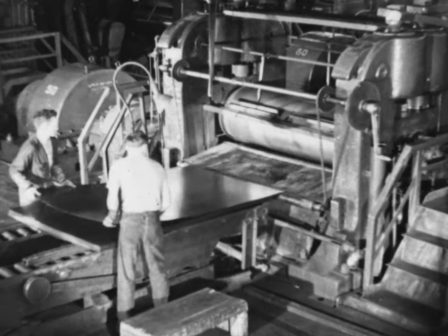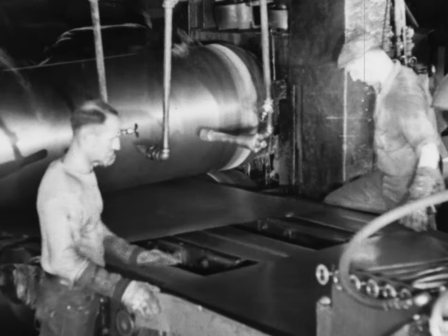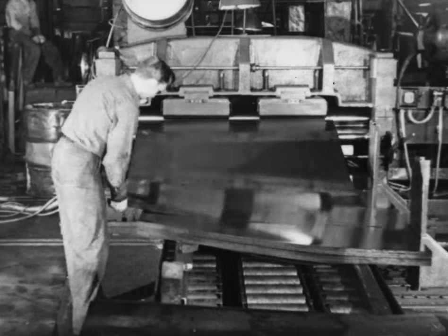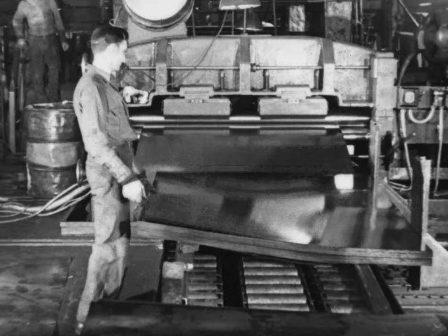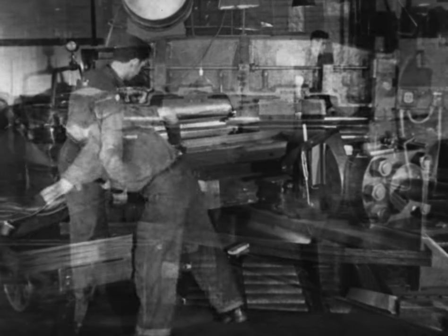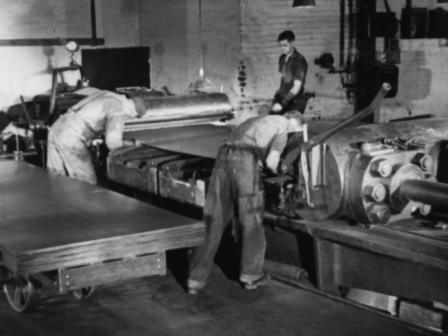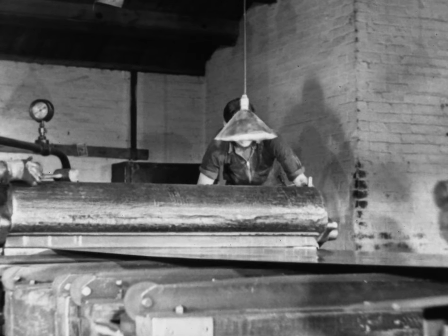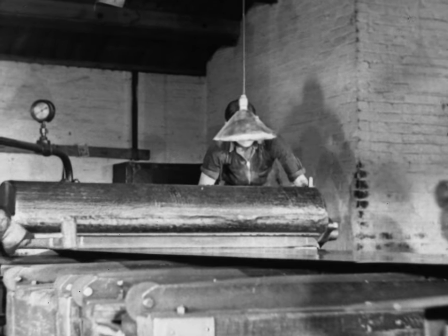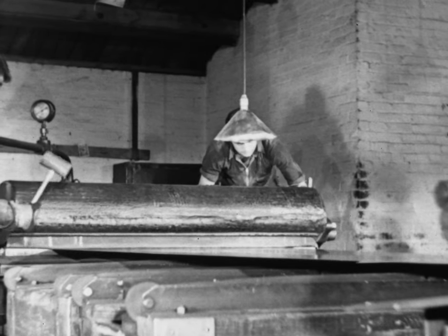Temper rolling adds three necessary qualities to sheets: flatness, a nice even surface, and a proper degree of stiffness. As the sheets leave the last stand of temper rolls, they pass through a roller leveler that further improves their flatness. And believe it or not, for absolute flatness, the sheets are stretched. The tone of the sheet when struck by a wooden mallet tells the operator when the sheets are really flat.